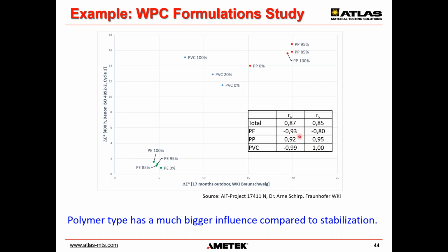If you look at the individual materials, I would say the correlation is actually relatively limited, completely statistical. And if you look at the numbers of the stabilizer content in the different formulations, it's surprising that it's not actually depending on the amount of stabilizers used. So it's relatively sensitive here. So it's not the best to do a correlation study for all of those materials. And no real statement can be made here on the overall correlation in this study.